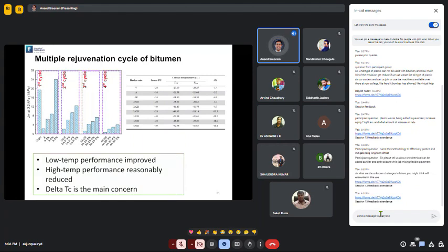based on BBR results. Essentially, what delta T of C tells us is that although we are able to meet the low temperature performance in terms of stiffness per se, the rate of change of stiffness is not the same when we keep recycling it. That means there is something happening in the material. Although we are able to rejuvenate it and meet some of the characteristics, it is still not the same as our original material. Something has changed in the fundamental chemical nature of this material that has still not become the same when we recycle it. One of the main reasons that we think that's the case is that something's changed in the chemistry, and we still need to figure out why. And we have to meet that demand.